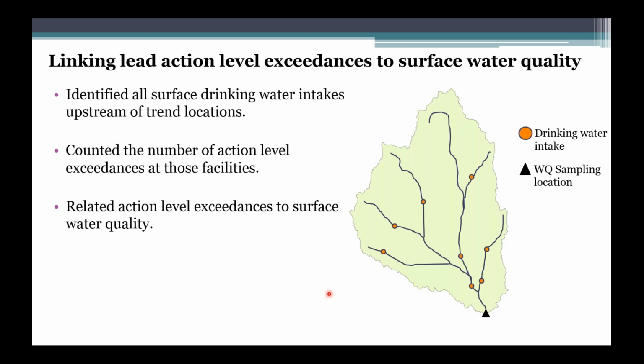So our approach was to define watershed boundaries for all of the trend locations, and I have the trend location marked out as a black triangle on this particular schematic. We then located all of the surface drinking water intakes upstream of the sampling location, and we counted the total number of lead action level exceedances in the basin. Okay, so the number of times when it was reported that there was an elevated lead concentration in the tap water. We then related the number of exceedances to the water quality at the monitoring location, and look for relationships that way.